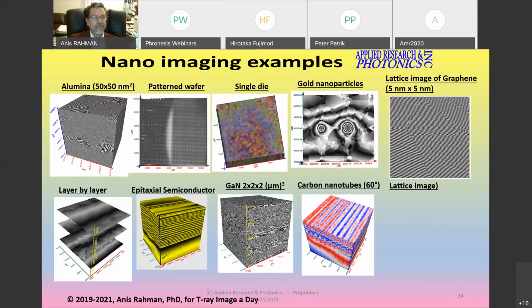On the left, alumina, which is an amorphous material, but an amorphous material doesn't mean that it doesn't have any lattice structure. It still has lattice structure, but those nano grains all have different lattice structure. That's what makes it amorphous. On the right, as you can see, this is the lattice image of graphene. So the graphene forms a much more regular structure than alumina.